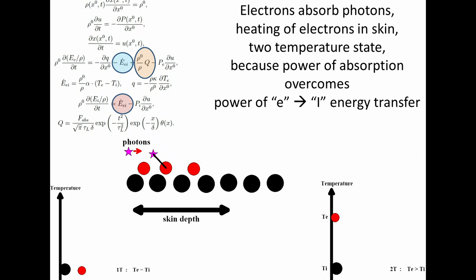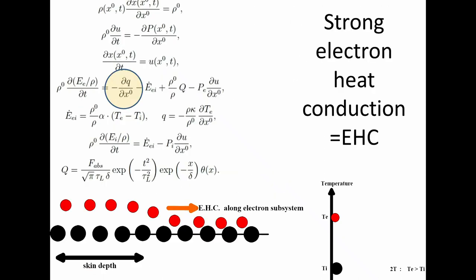Its power is much less than the power of laser if we use femtosecond lasers with very bright flashes. Therefore, they are hotter, much hotter than ions. Another important ingredient is this electron heat conduction term. In metal it is large, and this term transports energy absorbed at the skin depth here into the bulk of the metal.